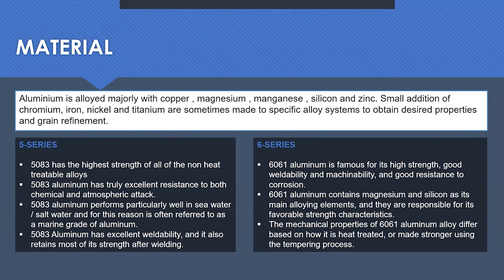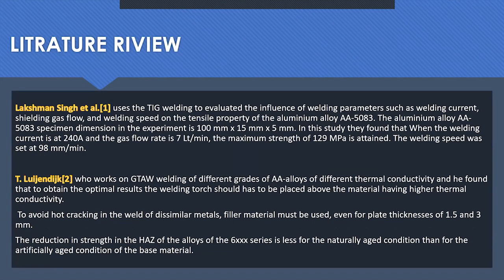5083 was in annealed condition and 6061 was in tempered hardness condition at T6. 5083 has the highest strength among the non-heat-treatable alloys, and due to its high resistance toward atmospheric attacks and corrosion, this grade of aluminum is known as the marine grade of aluminum. Then 6061 belongs to the 6 series of aluminum alloy, where magnesium and silicon are the major alloying elements, due to which the machinability and weldability of this material is very high, and the mechanical properties of 6061 are also very high. So now come to the literature review.